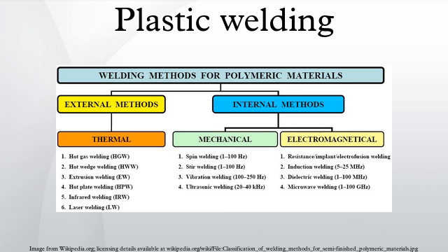RF welding is fast. This type of welding is used to connect polymer films used in a variety of industries where a strong consistent leak-proof seal is required. In the fabrics industry, RF is most often used to weld PVC and polyurethane-coated fabrics. This is a very consistent method of welding. The most common materials used in RF welding are PVC and polyurethane. It is also possible to weld other polymers such as nylon, PET, PEVA, EVA and some ABS plastics. Exercise caution when welding urethane as it has been known to give off cyanide gases when melting.